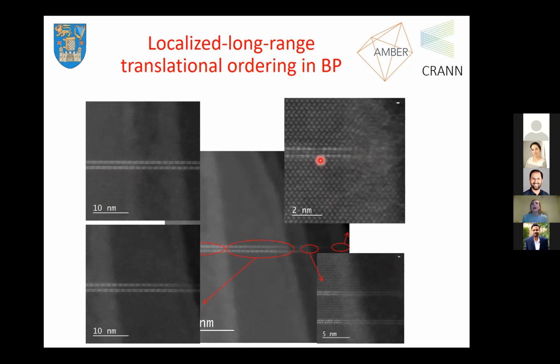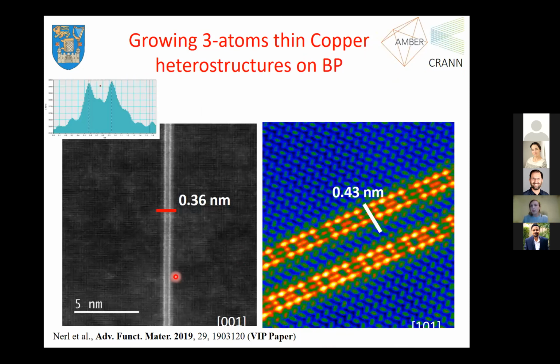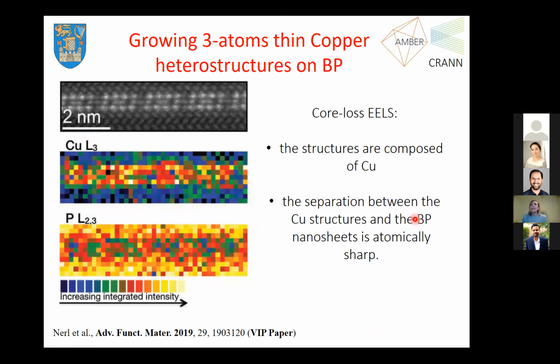So we were actually forming parallel lines of a metallic atomic species, in this case copper, on black phosphorus, which was quite unexpected. Again, we did all sorts of structural characterization on these lines. Here are these copper lines seen from 2 different symmetry directions. Here you have a projection of a width of 0.43 nanometer, here a projection of 0.36 nanometer. Again, astonishing is how regular this structure is. We did some EDS characterization, and there was absolutely no doubt that this was metallic copper building up as wires along the black phosphorus structure. We didn't see any oxygen. There was no oxide being formed. It was copper on phosphorus, nothing else to see there.